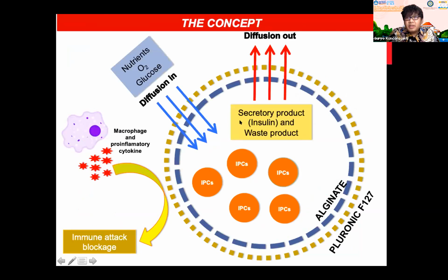And how about the concept of the IPC encapsulation? In the concept that we developed, we try to encapsulate the IPC produced by previous protocols, using alginate as a core encapsulation and double encapsulating or coating with the pluronics. And for success, again, the diffusion in and also the diffusion out should be achieved. For the diffusion in, the nutrient, oxygen, and also glucose can penetrate into the capsules, while the secretory product like insulin and also the waste product of the IPC itself can diffuse out. And also this encapsulation platform should provide immunoisolation ability.